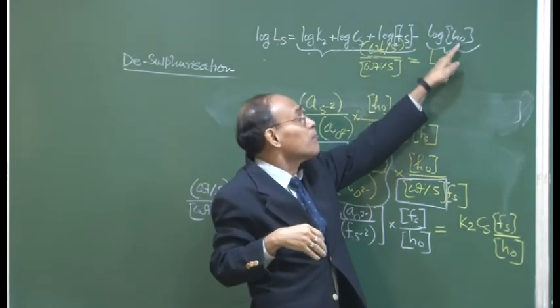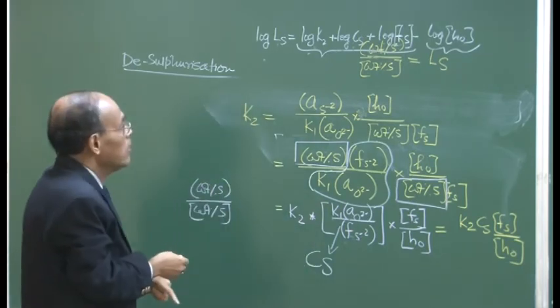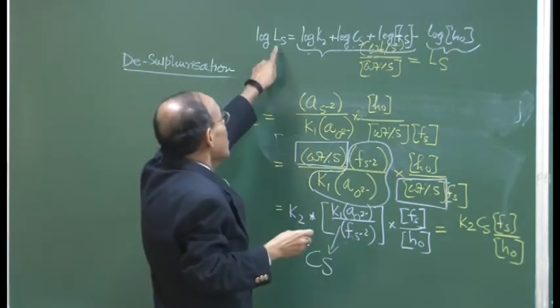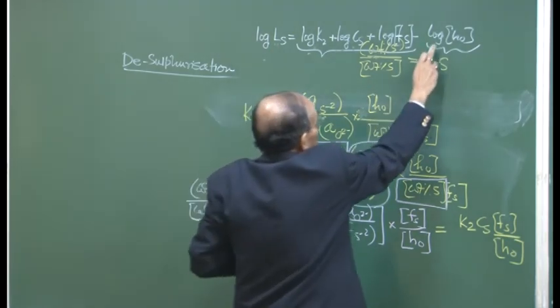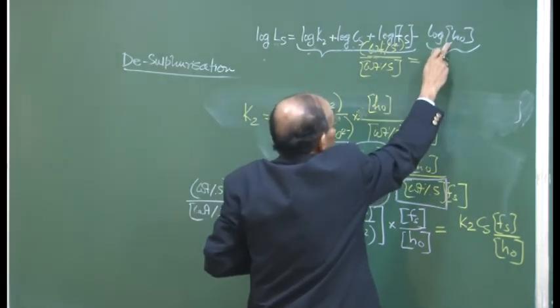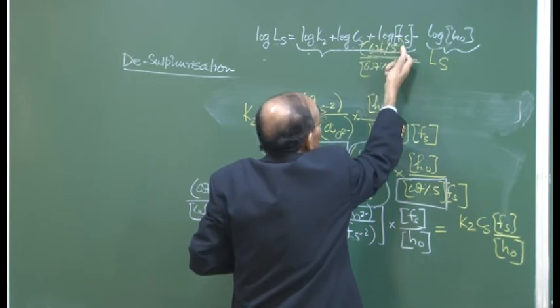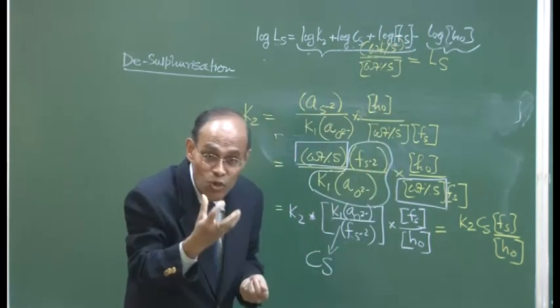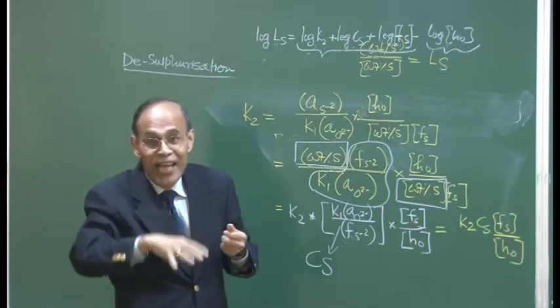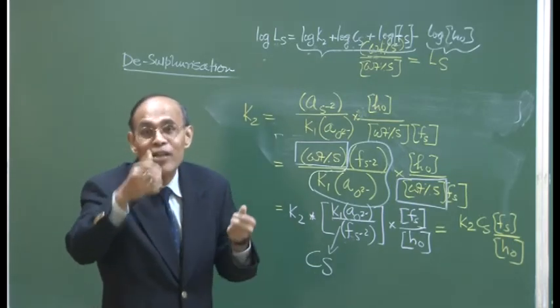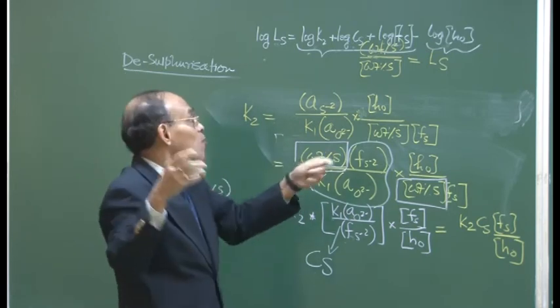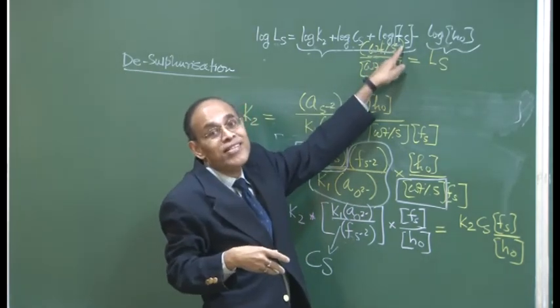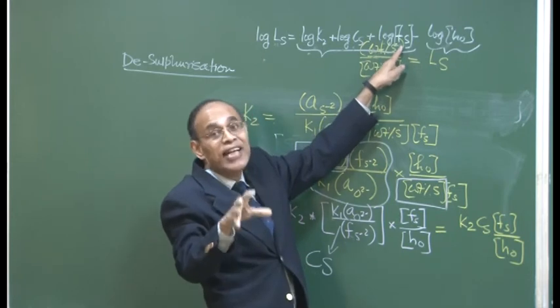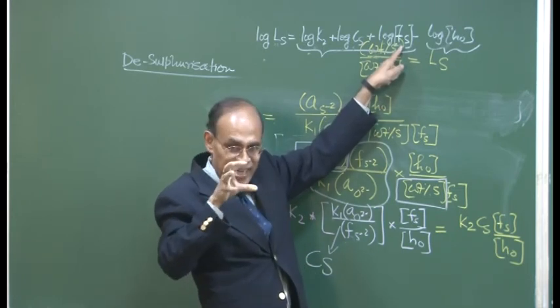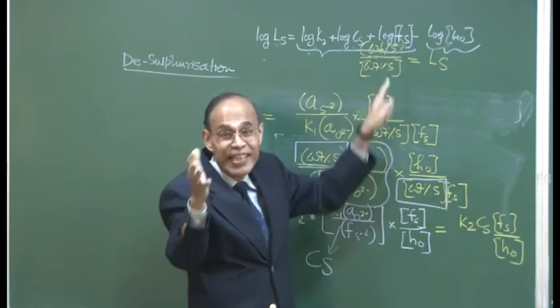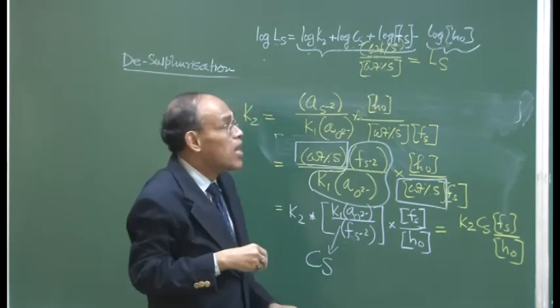The smaller the oxygen content of the melt, the greater will be the chances of getting a higher LS. So therefore, a smaller value of this essentially means we have a reducing environment. Log FS, a higher value of activity coefficient, essentially means that there should be some other elements dissolved which will not allow iron to bond with sulfur. So iron can let sulfur go, and that is the case when we say that the activity coefficient of sulfur in the melt is very, very large. Okay? And incidentally, because iron has a great affinity towards carbon, the presence of carbon increases the activity coefficient of sulfur in the melt itself.